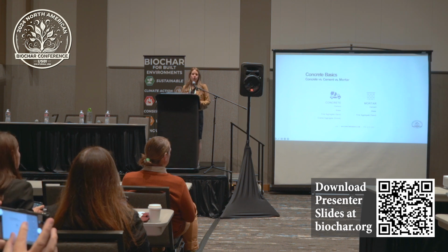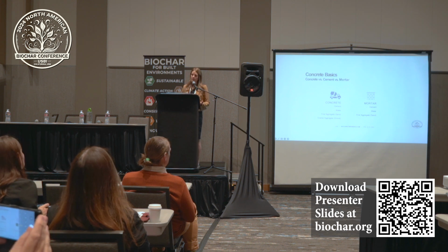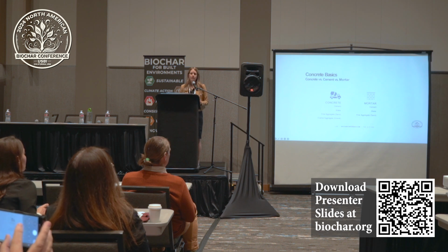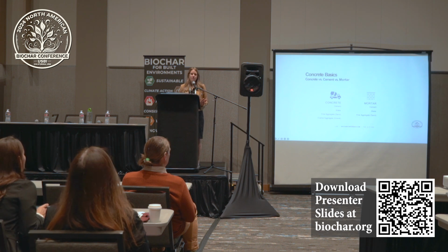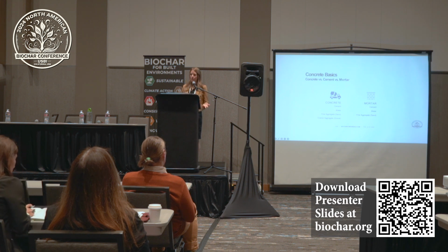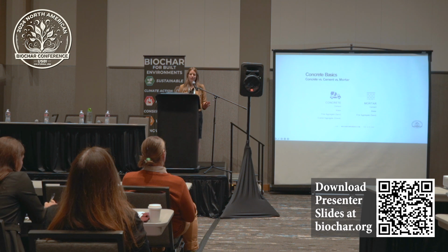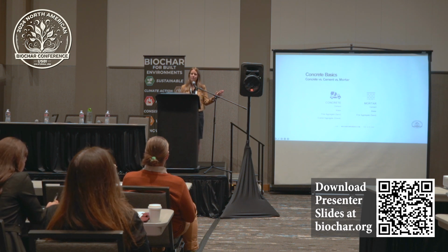So the real difference between mortar and concrete is that concrete contains coarse aggregate and mortar just has the fine aggregate. And the reason why I wanted to make this distinction is most of the work that we've done in my lab has been on mortars. The reason for this is that we can just do a lot more reproducibility with the same amount of materials. It just takes a lot less materials. And we've demonstrated, and others have demonstrated, that the properties and the trends that you see with mortars is the same for concrete. So there's no loss there, but I'll be using these terms kind of interchangeably, so I just want you to be able to track along. The laboratory tests we've done have been primarily mortars, but there's applications to concrete.